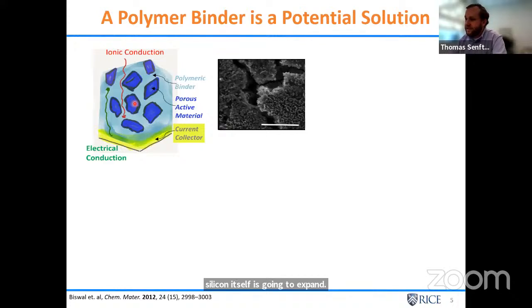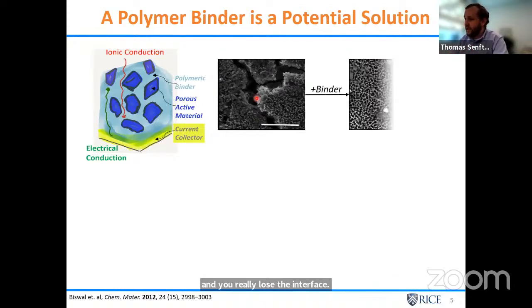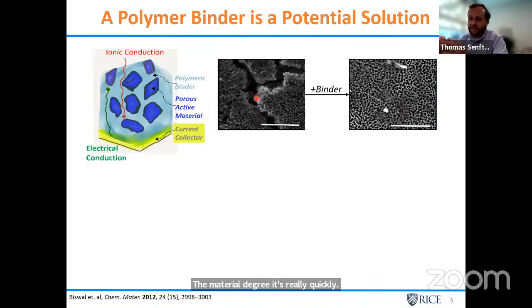So just to see this at the experimental microscopic level, what I've shown is a micrograph of the mesoporous silicon electrode, again, developed by the Biswal group, without any binder. And we see that after a couple of cycles, it fractures and you really lose the interface. The material degrades really quickly. If instead you embed the silicon particles in a polymeric binder, you can cycle it several times and maintain a nice structure, okay? So this is the goal.